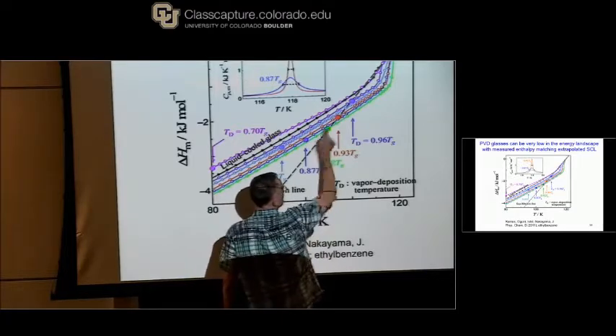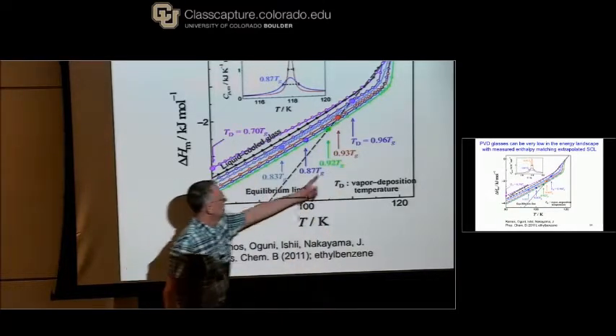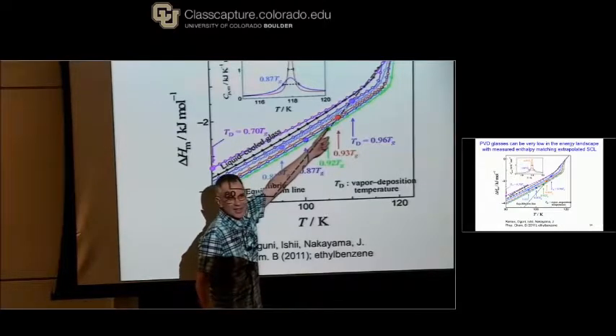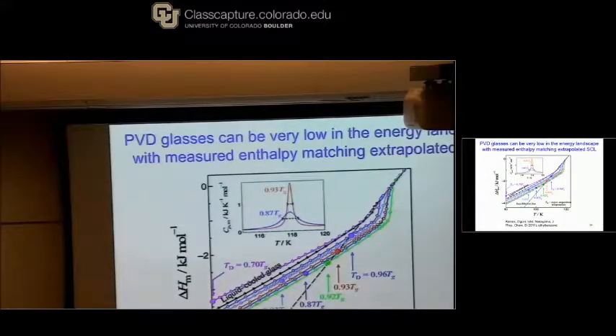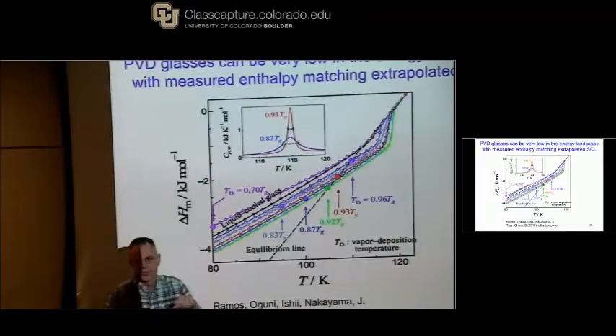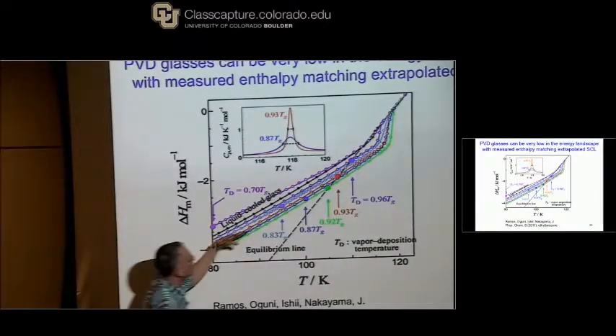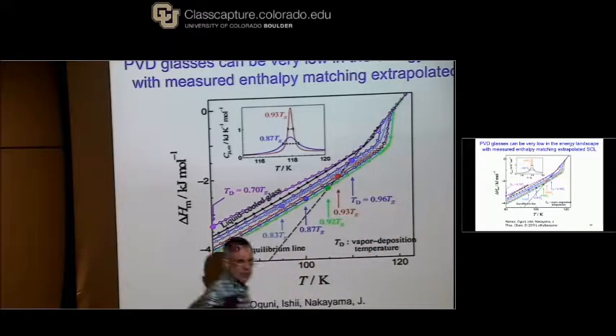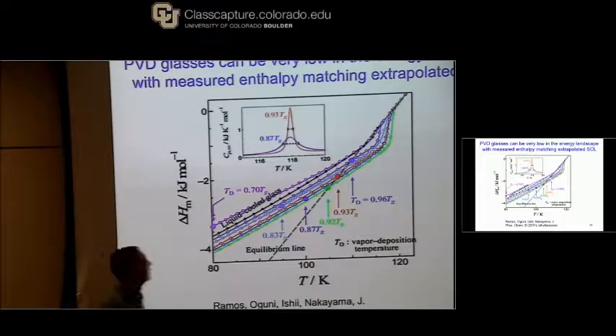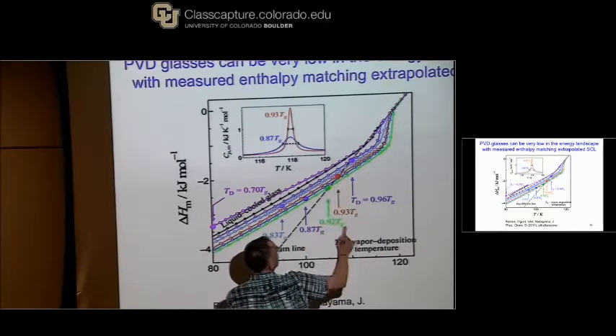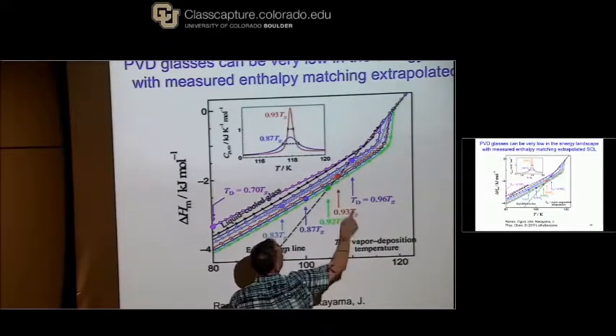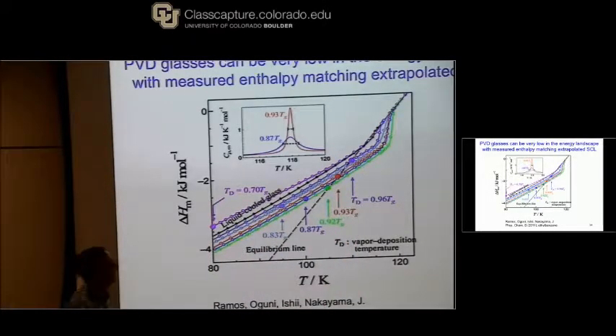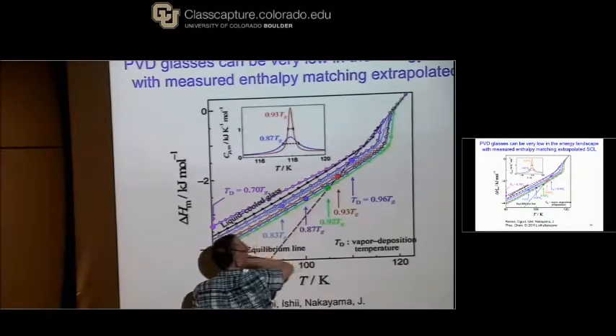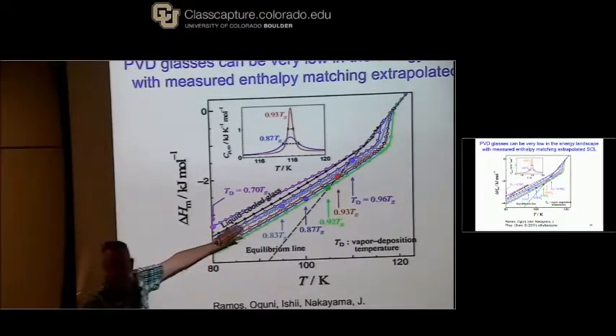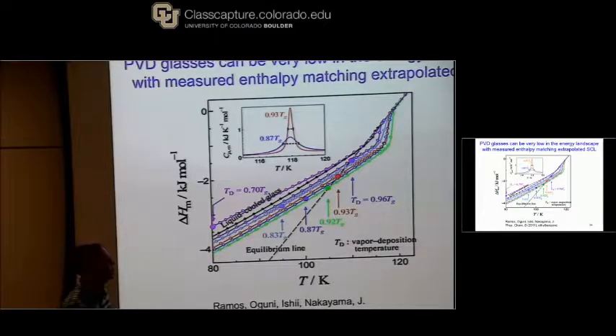This is my favorite point, the green point. So they deposit at 0.92 TG. They take that sample, they cool it down to low temperature, and now very carefully as they increase the temperature, they measure the heat capacity all the way up into the supercooled liquid. And then they integrate CP in order to get H. Okay? So that's where the green curve comes from. This point is what happens at 0.93 TG. Okay? And so its enthalpy in the glassy state is slightly higher than what happens if you deposit it at 0.92 TG.